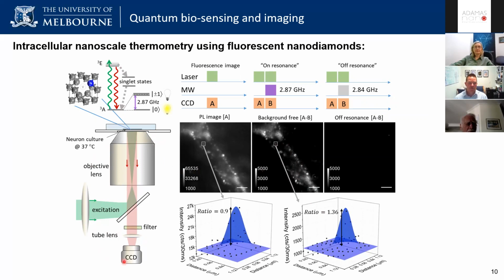And so we built this wide field imaging system, which was able to keep the neuronal culture stable at different temperatures. So basically we had a live cell imaging chamber that we would heat the whole chamber. So the objective and everything was at 37 degrees. We were able to show that employing different imaging sequences. So if we employ an image sequence where we take a standard fluorescence image, and then a fluorescence image with a microwave pulse, which is on resonance with the NV center, we can actually enhance the fluorescence image and reduce the background in that image just by taking advantage of the spin properties to do with the NV center. So we can get background free imaging, if you like, just by looking at that.